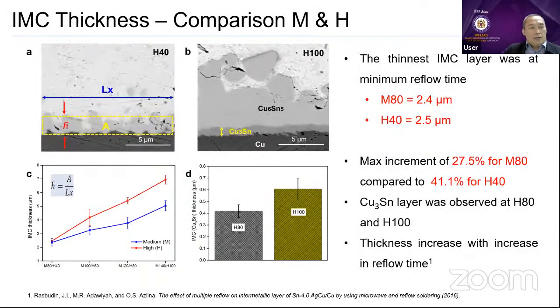Okay, and then I do have a very good student who ran this experiment. She did a very nice job calculating the thickness of each layer. So these are the thickness of those layers for the IMC. This one is for the medium and then for the high mode. And for sure, when we run for a longer time at high power, we can get a very thick IMC compared to the lower power and so on, right?